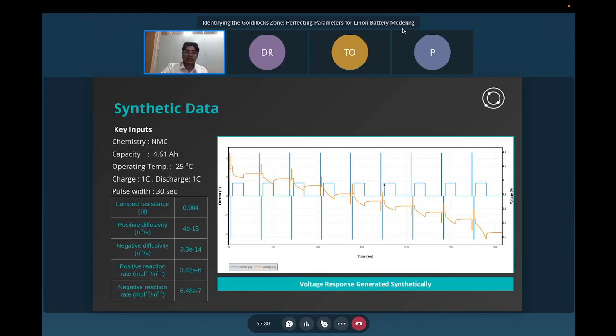Now, in this case, synthetic data was generated for an NMC cell, which is a 4.61 ampere hour cell. And these were the reference parameters that we started with. And as you would see, in a typical HPPC profile, you initially have a charge pulse, and then you have discharge and charge pulses, and then you remove the SOC, and you repeat these kinds of sequences till you go to the lower SOC value.